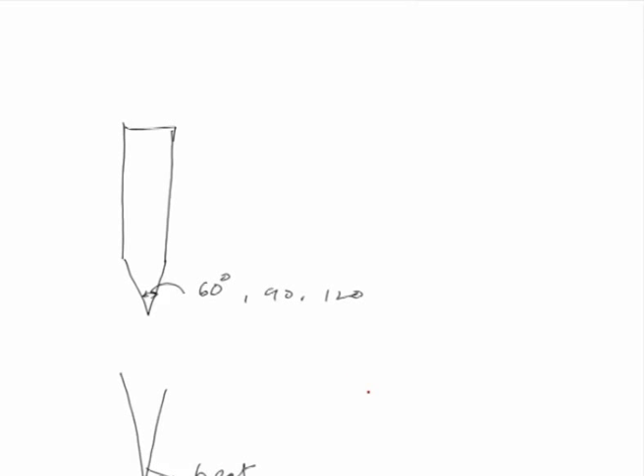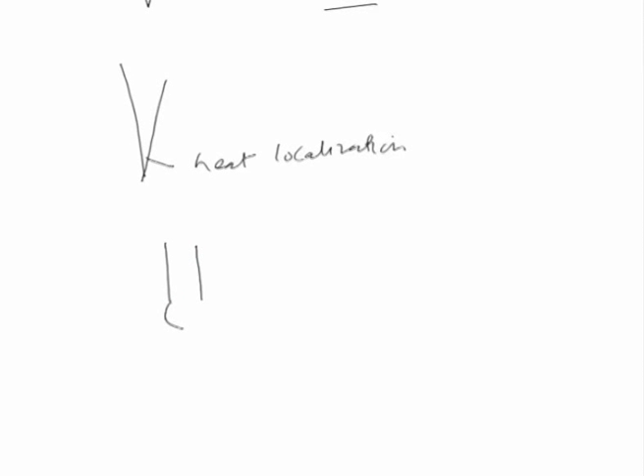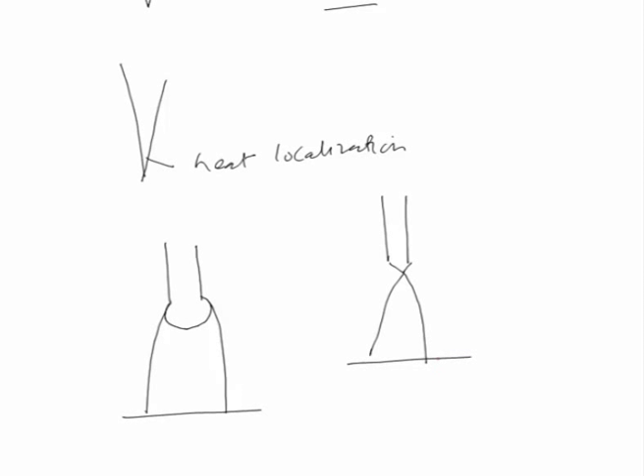So, the localization of heat in a very sharp tipped end of the electrode causes rapid degradation of the electrode tip, which in turn decreases the life of the electrode rapidly. And to avoid this kind of localization, it is preferred to have either the conical tip with a larger angle or a ball shaped tip, so that a very smooth and stable arc can be obtained instead of the case where a very pointed tip is used. This kind of tip causes high heat localization, while the heat localization is somewhat reduced in case of the ball shape.